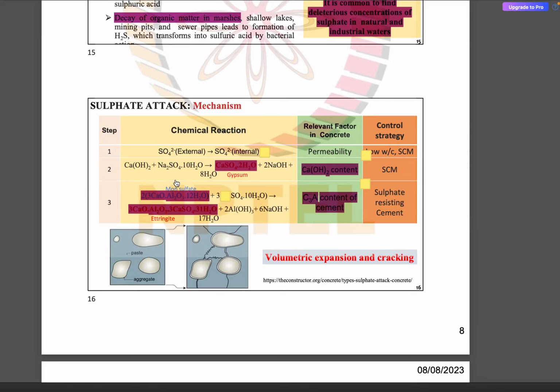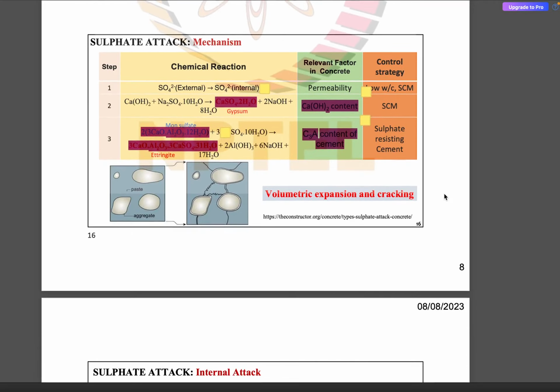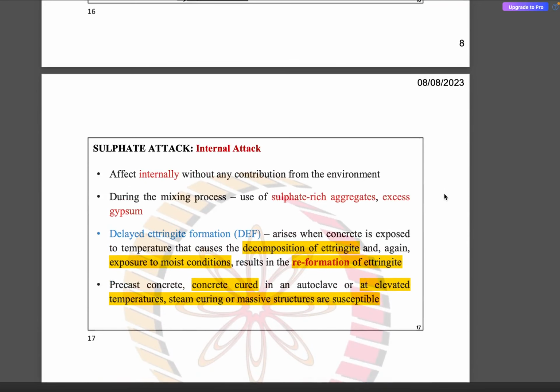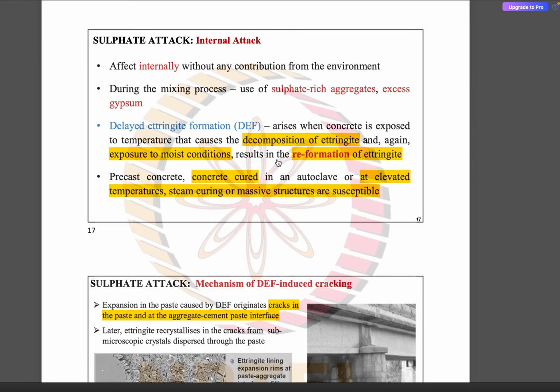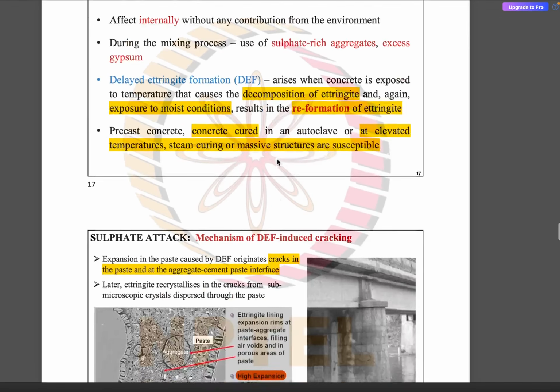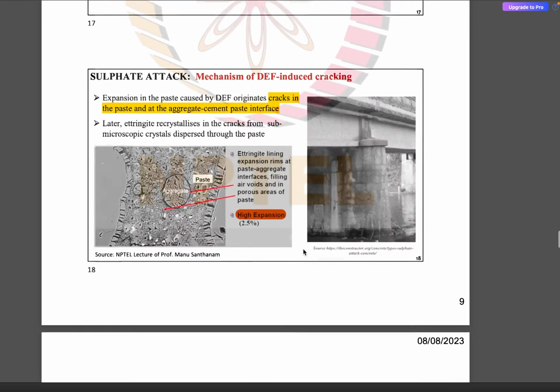As we saw, the reaction between the monosulfate and gypsum leads to the formation of ettringite. Whenever there is a presence of high C3A in the cement, that leads to high heat of hydration, and that leads to the formation of monosulfate, and later on, when it is conducive, the monosulfate transforms into ettringite, which is a needle-like structure. Because of the structure of the ettringite, it leads to the expansion within concrete, and that leads to cracking and other durability related issues. As I was discussing in the previous slide, the process of delayed ettringite formation leads to various durability related issues, and these are some of the effects due to the delayed ettringite formation.